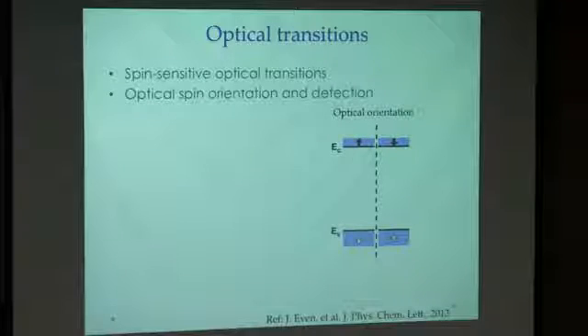So now I will talk in more detail about the optical transitions. These are the bands. With right circularly polarized light excitation, we excite those populations. We have spin polarization in the conduction band and valence band. Similarly, with left circularly polarized light, we excite the other pair of states. The measurement also works based on the same rules. Imagine that we already have some spin population in the valence band and some spin population in the conduction band.